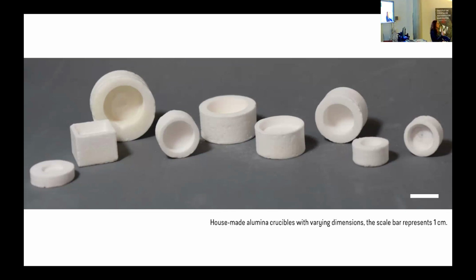You just use a single additive at a minimum amount with an advanced ceramic. You hand shape it. You put it into the CNC. You do whatever you would like to do, and then you sinter it. Okay. And we are at 99.5% of the theoretical density of alumina. If we optimize these things further, there are times we have reached 99.8. So it's almost the same.